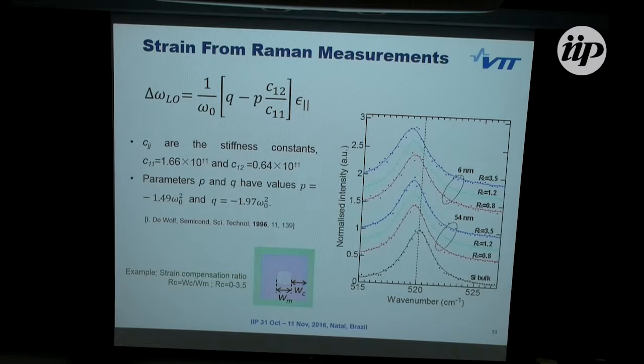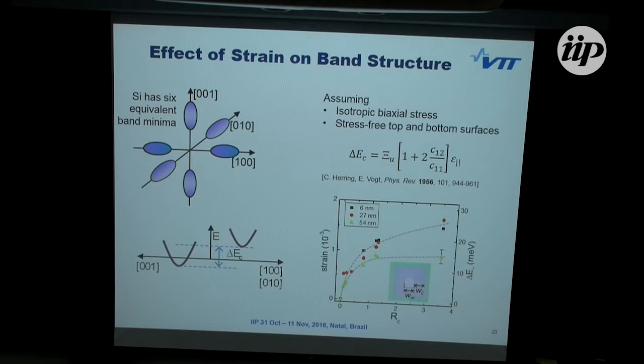And this then translates to this kind of numbers in this set of samples. So this is now the ratio of these lengths here, and then this is the strain. And there are three different thicknesses or different samples. And the strain can go with this, let's say, geometry, up to 0.15%.